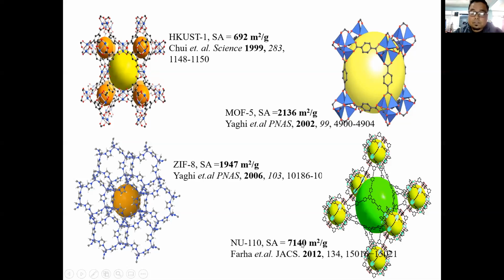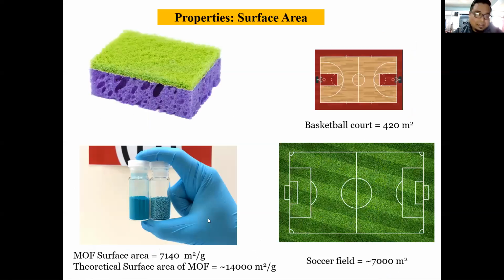Similarly, the highest one reported till date is NU 110, which has a surface area of around 7,140 meters square per gram. This is very high. So perspective wise, if I show you a soccer field whose surface area is actually 7,000 meters square, that means if you take 1 gram of that NU 110, let's say it must be like this much amount. So the surface area will be almost equal to around a soccer field. So that means it is highly porous. So whenever any material is highly porous, we can always think of a lot of properties like the adsorption properties, the separation properties. So all this comes into play for its role as functional materials.